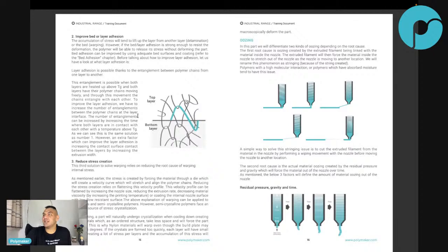So then, crystallize when cooling down? Crystallization doesn't matter if you cool down or if you heat up. The reason for cooling down is that after you create the crystals, you need to continue cooling down so that you freeze these crystals. But if you heat up, then you will also create the crystals, but then you will destroy them.